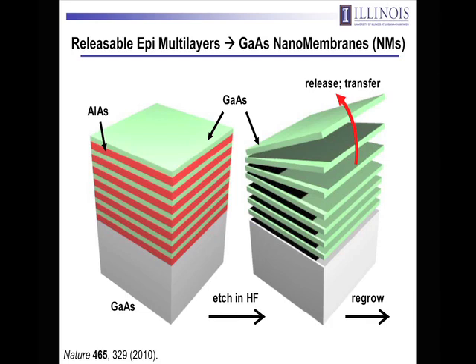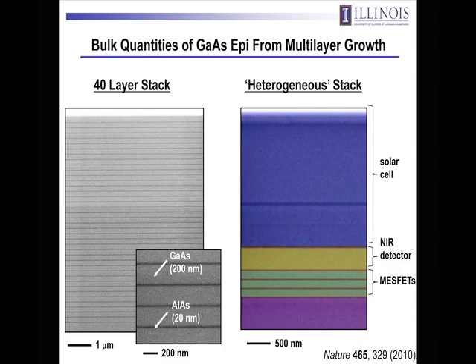So it's a way to really adapt existing thin film growth techniques to allow you to create bulk quantities of high-quality semiconductor material in a cost-effective way. That's the scheme, and that's the idea. It's multi-layer epitaxial liftoff, and you can actually do that pretty effectively. This is an example of a 40-layer stack of 200 nanometer thick layers of gallium arsenide separated by 20 nanometer thick layers of aluminum arsenide. Again, etch down through the stack, expose the sidewall, dunk it in HF, and off comes bulk quantities of gallium arsenide nanomembranes.